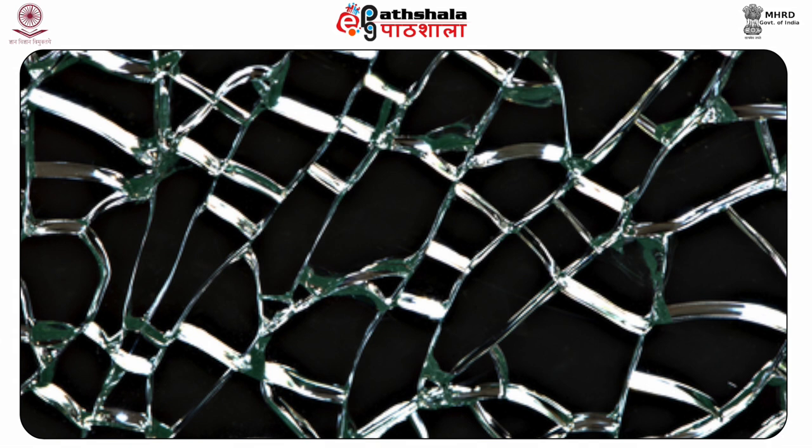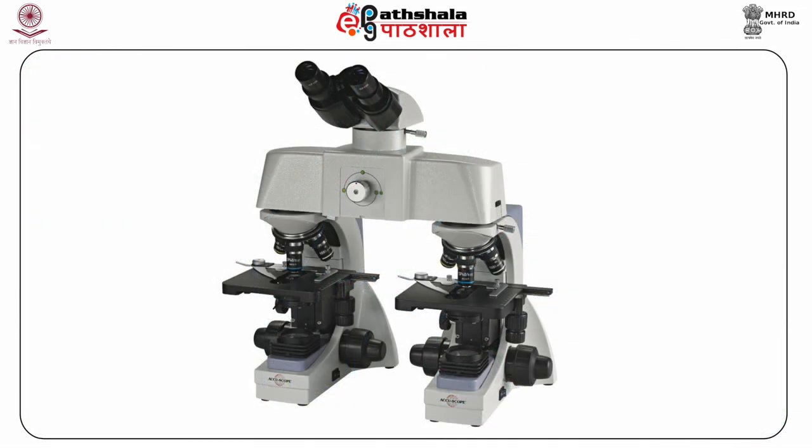A complementary lateral fit along the broken edges over a length of 1/4 inch or more establishes that the two glass fragments were continuous before breakage. By naked eye or under a microscope, we should search carefully the edges of the samples, which will exactly fit into each other, taking into consideration the factors contributing to the matching, such as general appearance, color, edge thickness, shape of breakage, and all the irregularities and striations near the broken surfaces.